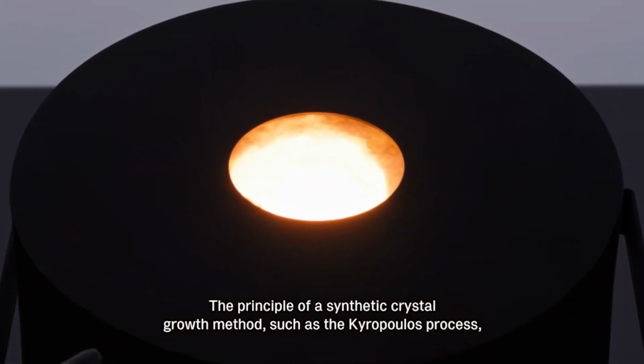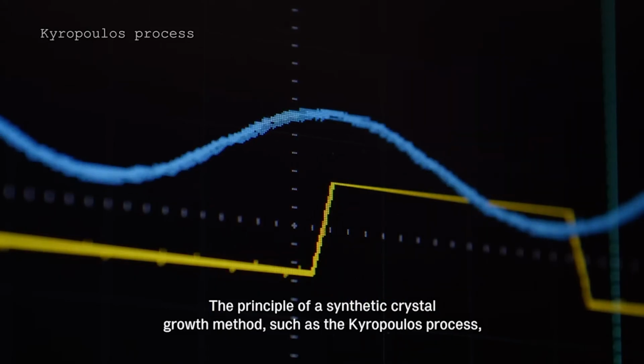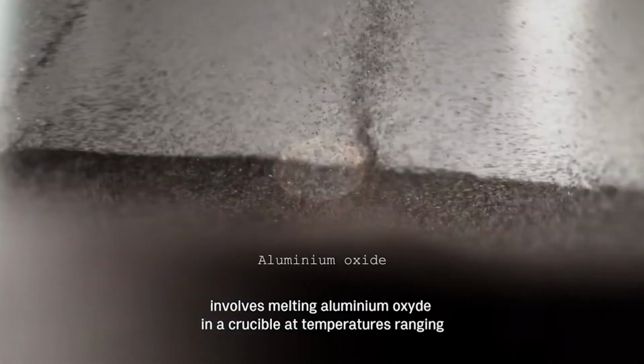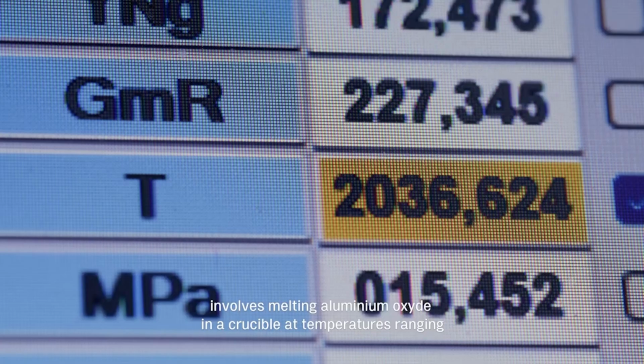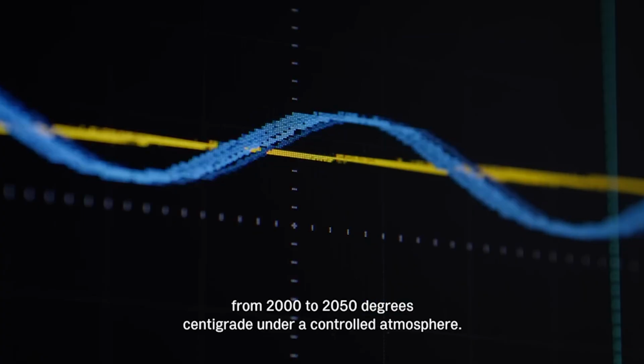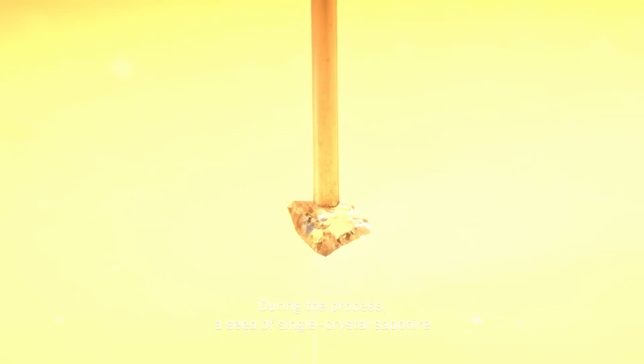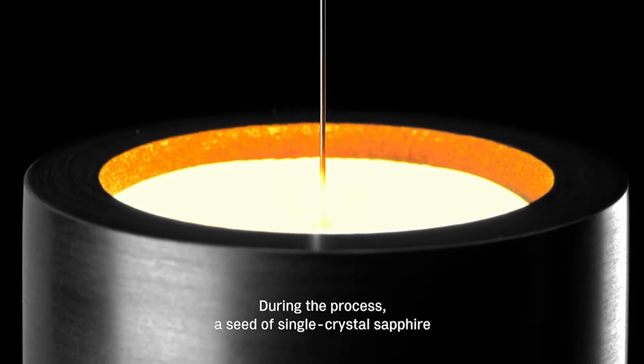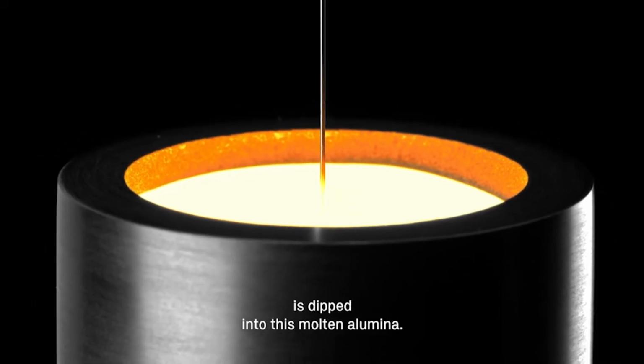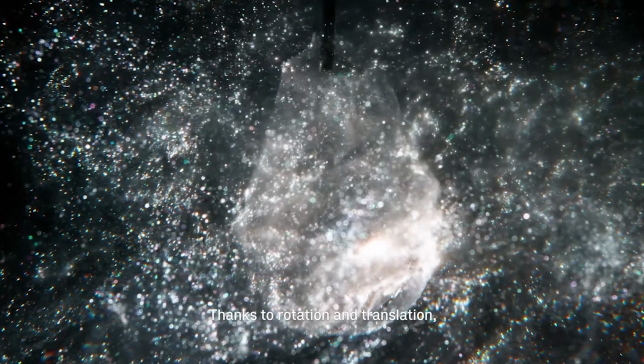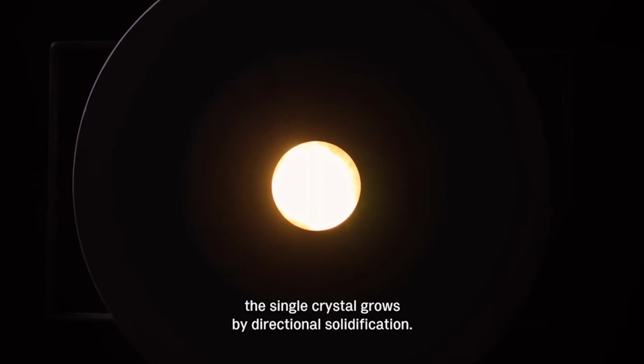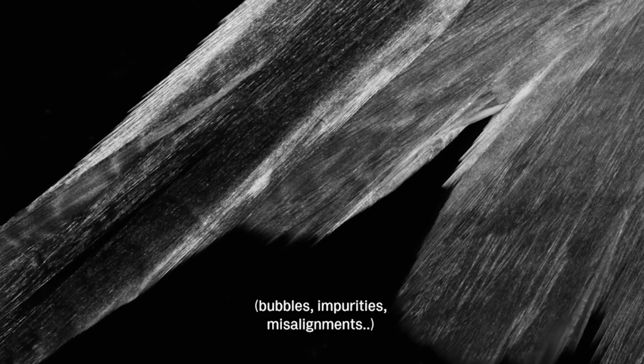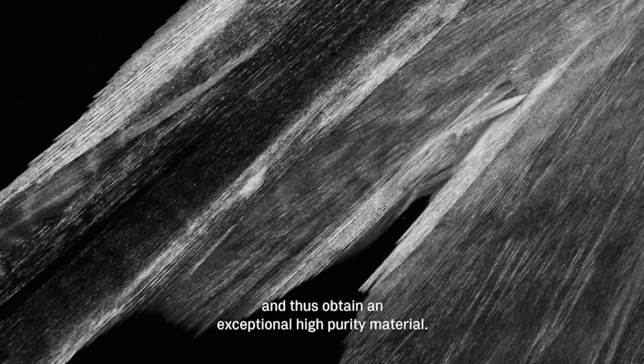The principle of a synthetic crystal growth method, such as the Kyropoulos process, involves melting aluminium oxide in a crucible at temperatures ranging from 2000 to 2050 degrees centigrade under a controlled atmosphere. During the process, a seed of single crystal sapphire is dipped into this molten alumina. Thanks to rotation and translation, the single crystal grows by directional solidification. The growth rate of this seed crystal is infinitely slow so as not to generate any defects in the crystal, bubbles, impurities, misalignments, and thus obtain an exceptional high purity material.